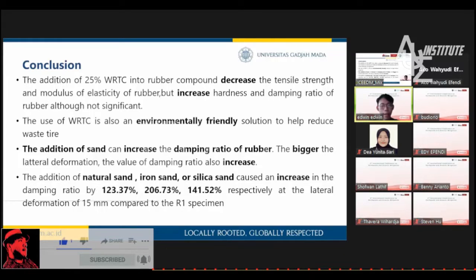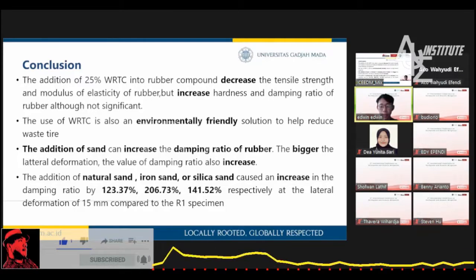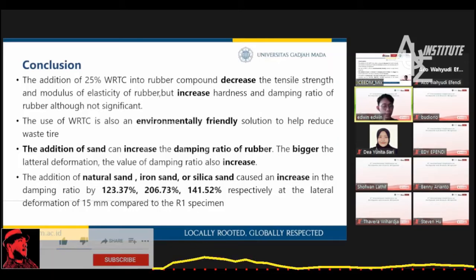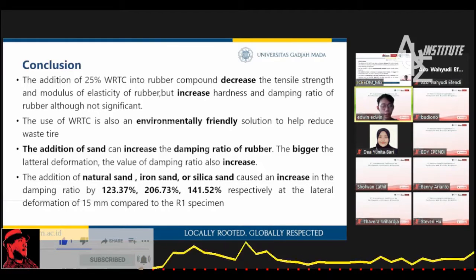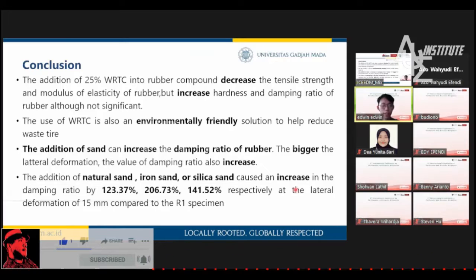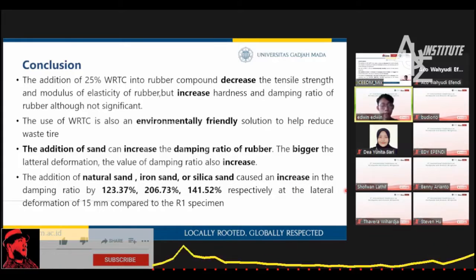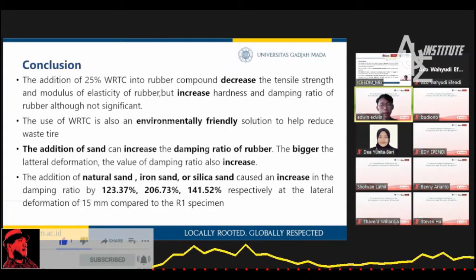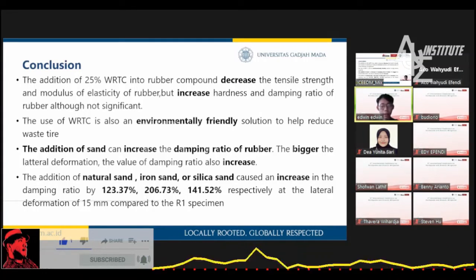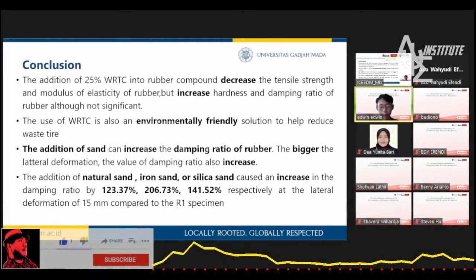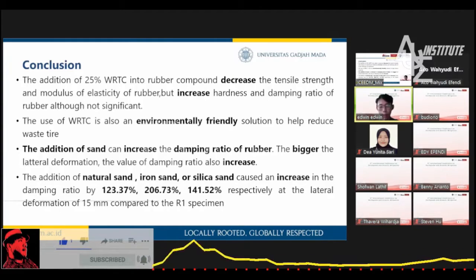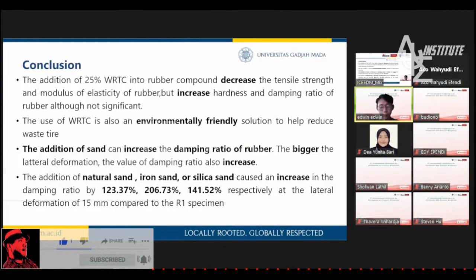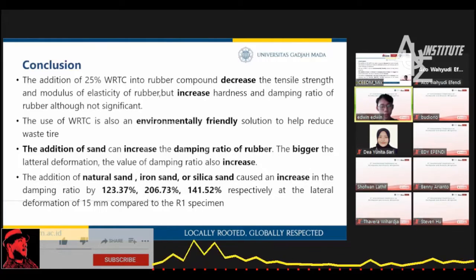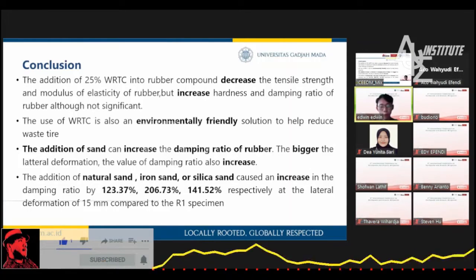Third, the addition of sand can increase damping ratio of rubber. As the deformation increases, the value of damping ratio also increases for test specimens with addition of sand. Fourth, the addition of natural sand, iron sand, or silica sand caused an increase in the damping ratio by 123%, 206%, 141%, respectively at the lateral deformation of 15 millimeters compared to the R1 specimen.